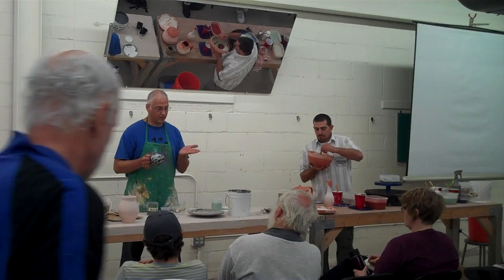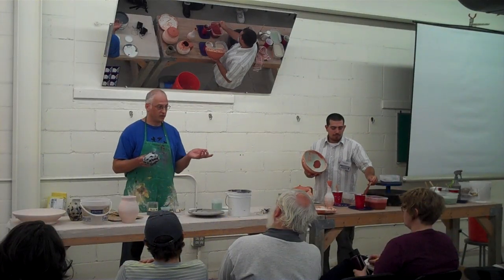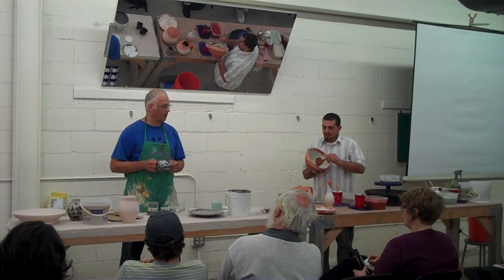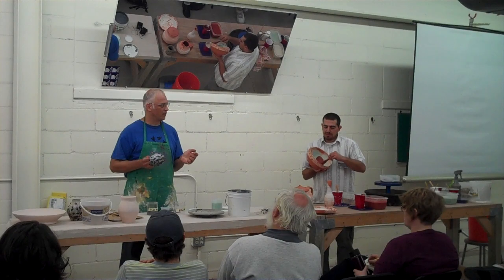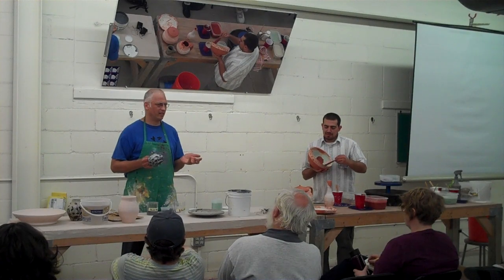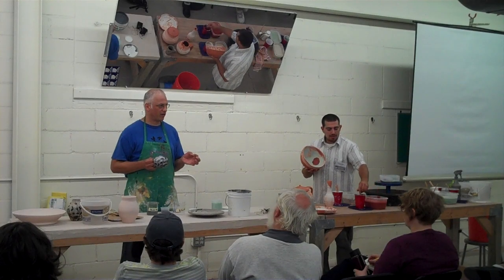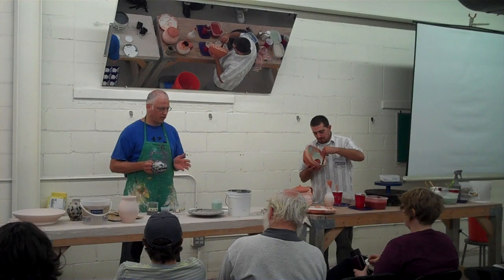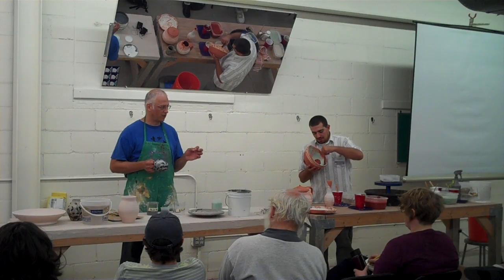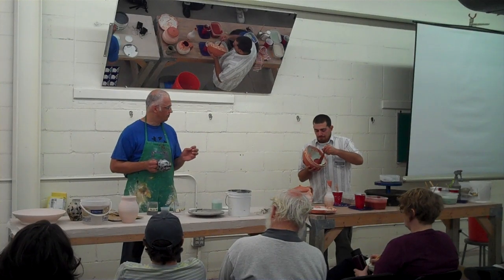I used to use equal parts. Someone told me back in college, to get black, just put all the oxides together and you get a really heavy metal. Maybe it's Don White's recipe or something like that. But I realized that I don't really need so much cobalt and manganese. They're very powerful colorants when they're with iron. So I end up using mostly iron oxide, and I put in a little bit of cobalt and manganese, and I also put in a little bit of frit, just to help it.